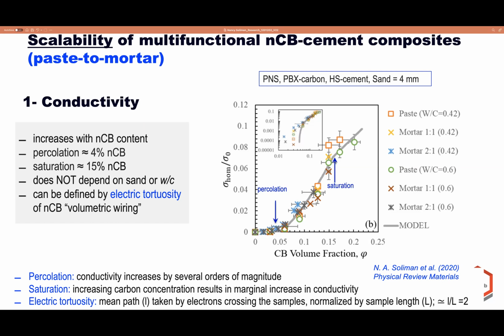So we found that by fine-tuning the carbon volume, we can reach a tortuosity value of 2. This means that the path the electron takes is only twice the length of the sample, and this is very important when designing electrical conductivity at engineering scales.